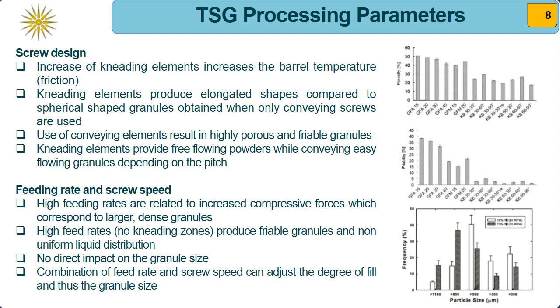Lastly, the feeding rate and the screw speed are very important, and it has been found that high feeding rates are related to increased compressive forces, which correspond to larger, denser granules. High feed rates with no kneading zones produce friable granules, as we mentioned before, but it has also been observed that there's a non-uniformity in the liquid distribution. Also, there was no direct impact of the screw speed on the granule size. However, the combination of the feed rate and the screw speed can be adjusted to the degree of fill and thus the granule size. This can be seen on the bottom graph on the right, where we have the particle size from two different degrees of fill of the extruder. So we can see that the higher the degree of fill, when it's around 70%, we obtain larger particle size of the granules.